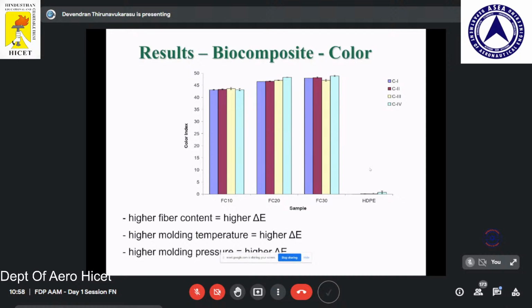So these are the results of the color fading analysis. Here the higher fiber content has a higher ΔE, and the molding temperature is high. With less fiber content, only about 40 to 43% is there. So if we increase the fiber content, the value increases. I'm trying to say that if you increase the fiber content, the color index is going to increase.